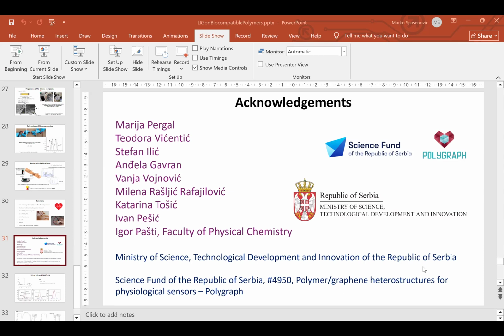But this LIG formation process is an interplay of heating and melting, I think, of the top layer of the polymer, and then reforming of these bonds to form graphene also happens in an atmosphere. So I think it's very difficult to quantitatively, let's say, give a theory on how the wavelength would correlate with the quality and yield of the material. But people have noted that you can also change the atmosphere, maybe put a nitrogen atmosphere and dope the graphene, etc. Maybe Spiros has a better answer.